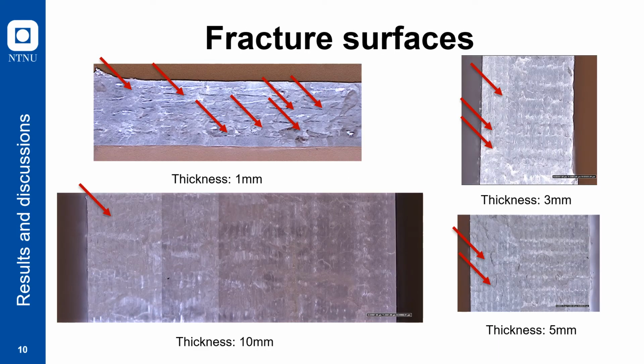And this is how the fracture surfaces look under the microscope. As you can see, with the increase in thickness, there's a tendency to have fewer defects and voids on the fracture surface. And especially for the 10 millimeter thickness, the fracture surface looks really good compared to the rest.